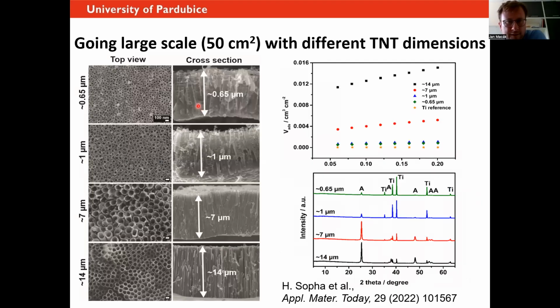And recently, on efforts of my colleague Dr. Hana Sopha, she actually was able to grow really, really nicely thick layers on titanium of this 50 square centimeter with different dimensions. So this is absolutely very recent. And look at the thicknesses. So we were able to get from 1 micron to 7 up to 14 microns. Now we are trying to push the limits even more.